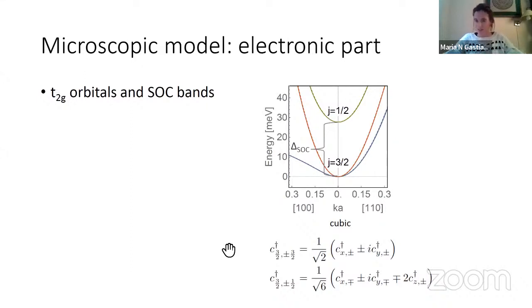Before going into the coupling, I have to say a few words about the electrons. I told you what the phonon is, and now I have to give you a brief description of the electronic part. So in strontium titanate, you have the conduction band around the zone center. It can be mostly described by the three t2g orbitals, the xz, the yz, and the xy, and then you have to add spin-orbit coupling, because the Fermi energies that you're at are comparable to the spin-orbit coupling energy split. Here I'm showing this explicitly. The three t2g orbitals would be degenerate. As soon as you switch on spin-orbit coupling, the six-fold degeneracy is split into a doublet and a multiplet down here. Then you start filling up those bands, and these Fermi energies are going to be of the order of this spin-orbit coupling gap.